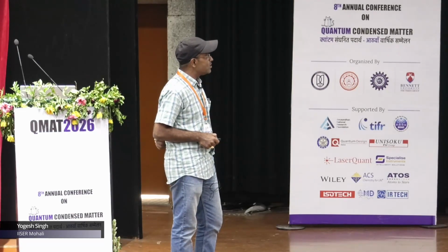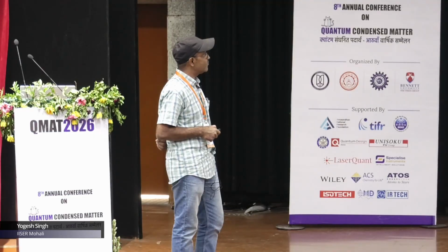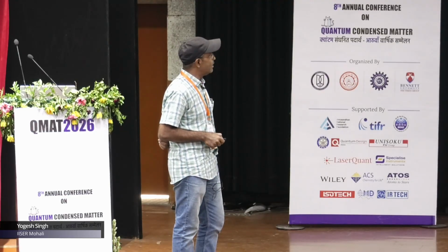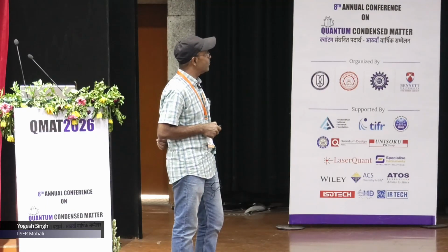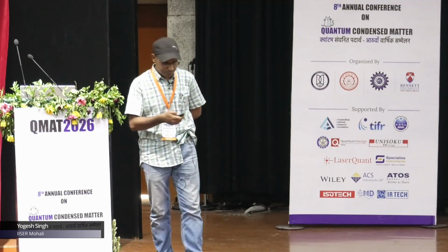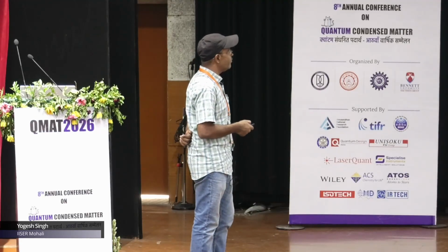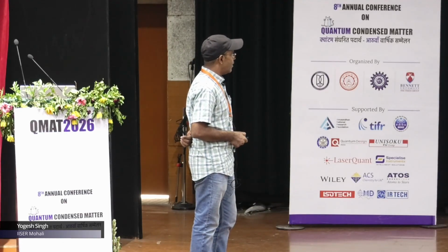So the Fermi velocity of the tube is the smallest, whereas the density of states of the tube is the largest. And the Fermi velocities of the ellipsoids are largest, although they contribute a very small fraction of the density of states. Okay, so we will use these later.